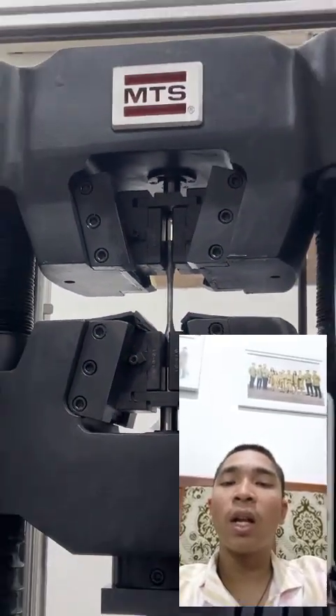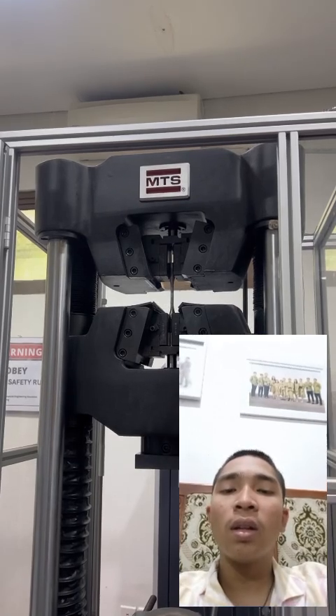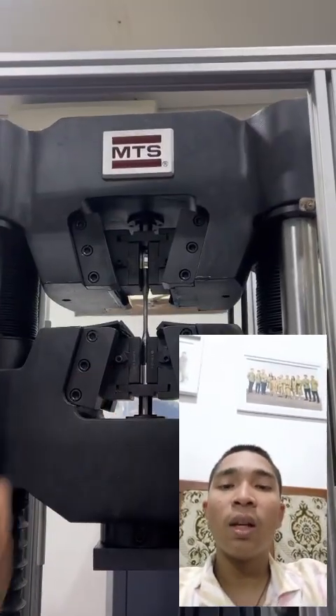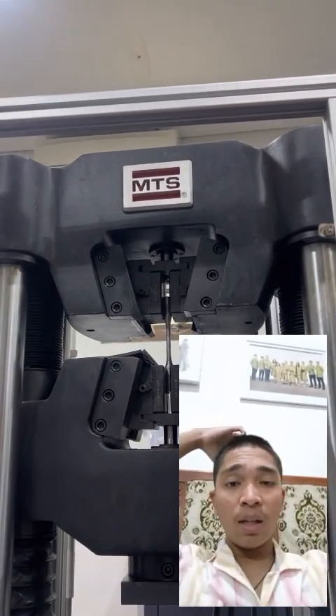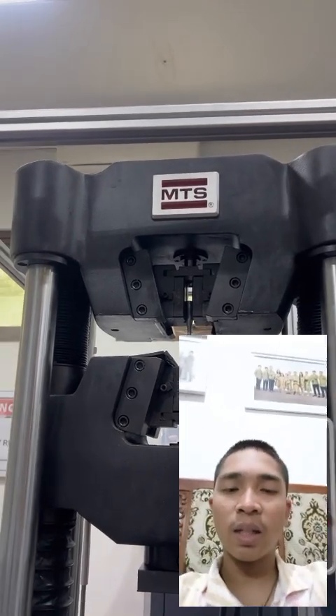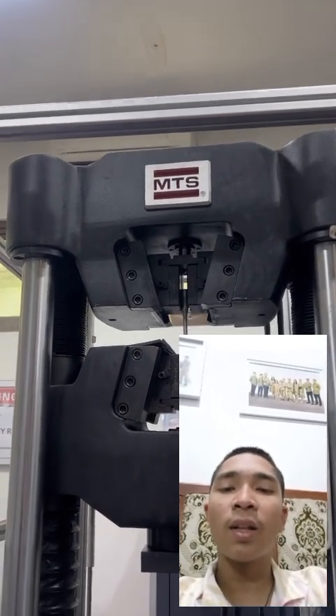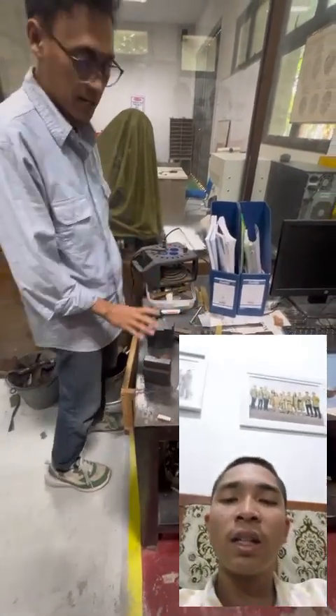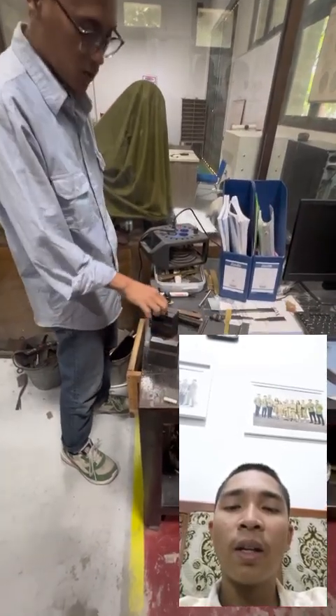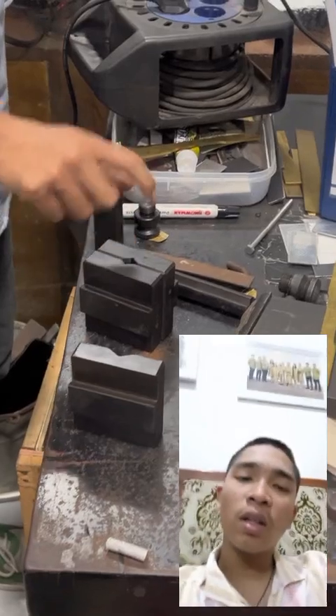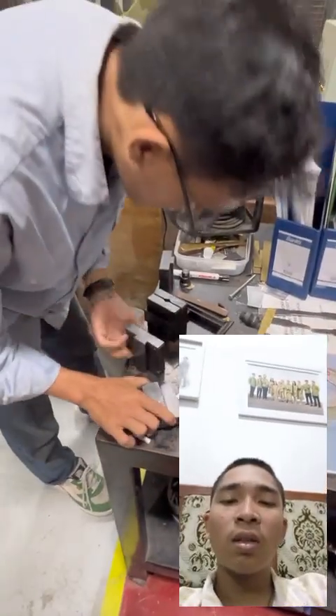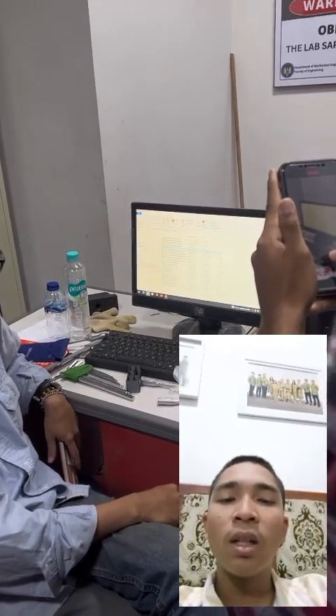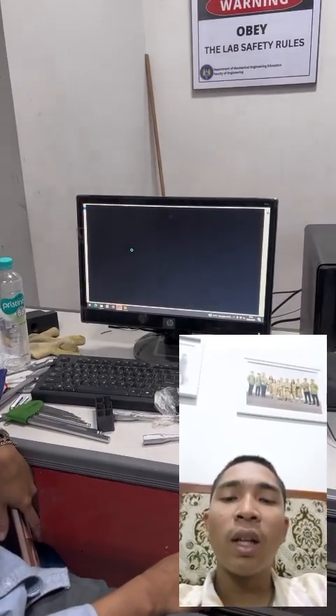The graph shows the relationship between load in kilonewton and actuator displacement in millimeter. The curve increases and the specimen carries more load. It reaches a peak point, or peak index, and then decreases sharply at the break point, or break index. This curve is typical of the 3-point bending test. Load drops after maximum, a sudden drop after failure. Parameter value: span 128 mm, the distance between the two supports in the 3-point bending test.